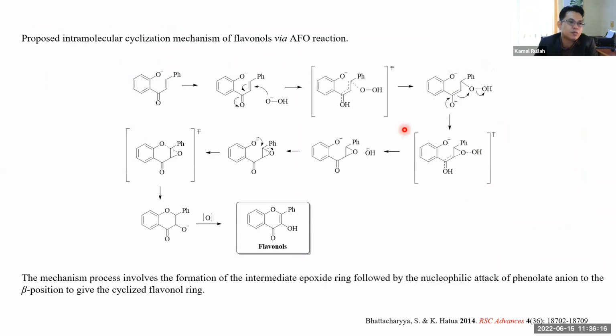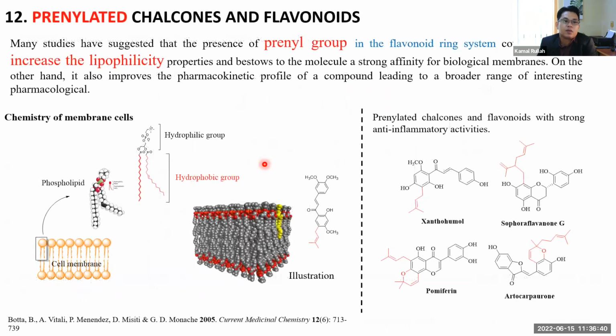And this is the proposed intramolecular cyclization mechanism of the flavonol via the AFO reaction. Importantly, it gives the oxidation of the double bond here, and then it can be activated to the nucleophile at this position. Next, we try another idea. A prenyl group in the flavonoid ring system could potentially increase the lipophilicity and bestow on the molecule a strong affinity for biological membranes. So it should give us more active compounds if we apply the prenyl group to our compounds.